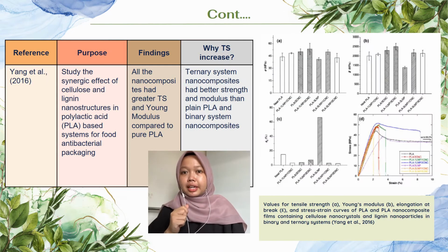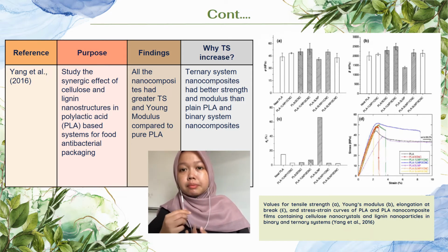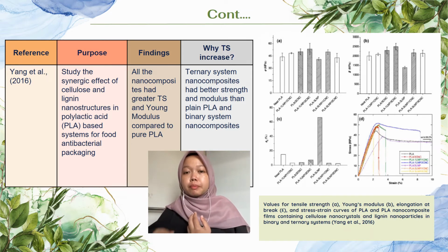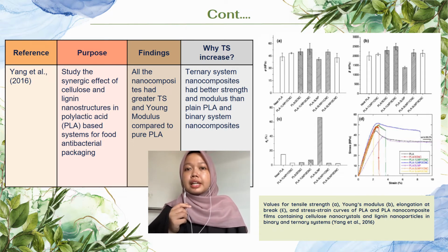A study by Yang et al. showed the synergistic effect of cellulose and lignin nanostructures in polylactic acid based system for food antibacterial packaging. It shows that all the nanocomposites had greater tensile strength and Young's modulus compared to pure PLA. This is because ternary system nanocomposites had better strength and modulus than plain PLA and binary system nanocomposites.